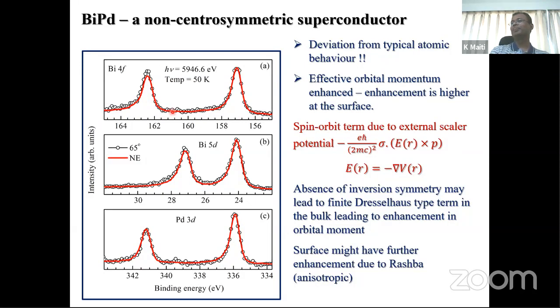So when we were trying to think what could be the reason, what we find is that in the solid you have an effective electric field because of this lack of inversion symmetry, even in the bulk, which can give you an additional contribution to the orbital moment. Okay, so this will enhance the orbital moment compared to the atomic picture, and we feel that could be the reason for this enhancement of the branching ratio.